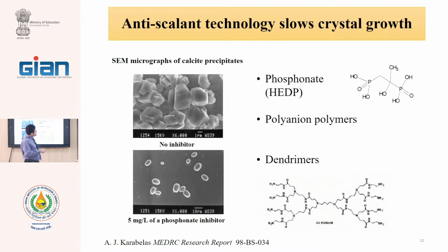You see that after producing these crystals, all connected together and produce bigger particles or produce a layer on the membrane surface. In this case, with polymers, the polymer connects to the produced crystals and does not allow more growth.